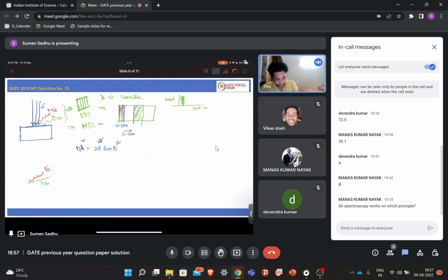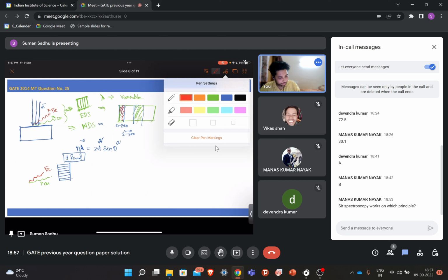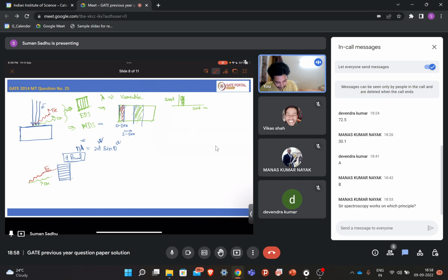Now you place a single crystal here which has a certain d value. The d value of this crystal is fixed. So it will scatter this iron X-ray to a certain angle and this copper X-ray at a different angle. Depending on which element you are measuring, your detector is placed here or here.